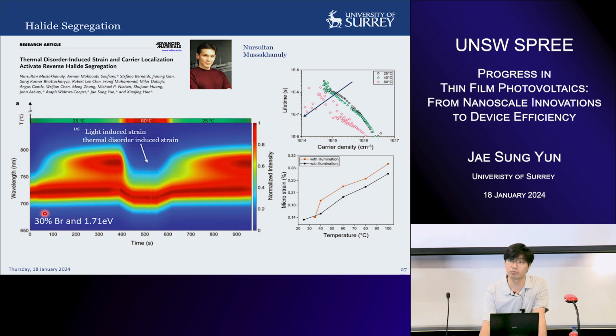If you see, that's the 30% bromide material with a band gap of 1.71 eV, and under illumination at 25 degrees, you can see that the highest PL peak appears here, and as we've seen before, it separates into iodine-rich and bromine-rich, wide band gap and narrow band gap regions. So there are now two peaks here, and when we suddenly elevate the temperature up to 80 degrees, you can see that the PL peak phase segregation is suppressed. And when we cool the temperature down to 25 degrees, the phase segregation appears again. So it's clearly showing that the phase segregation is a temperature dependent process.